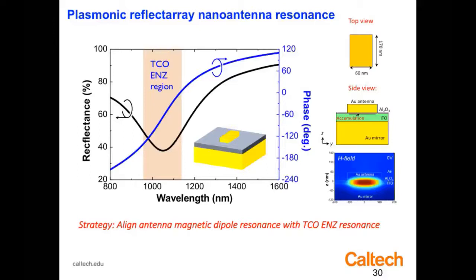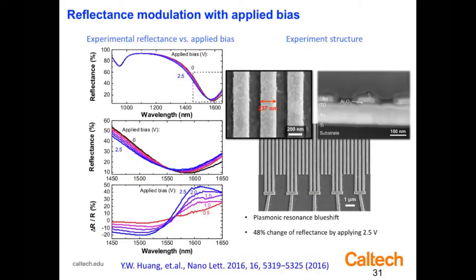So this is what they look like. This is what the little transistor-like devices look like. And this is at 1.5 microns in the telecom band, the modulation here of the reflectance. In a relative sense, the reflectance is changing by about 50%. The overall reflectivity is low. It's a little bit inefficient, but it turns out that that's not a major shortcoming. We can still use this kind of device.